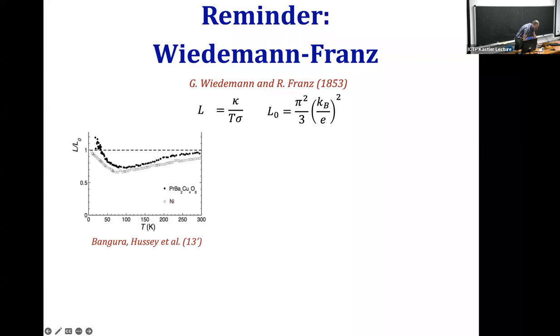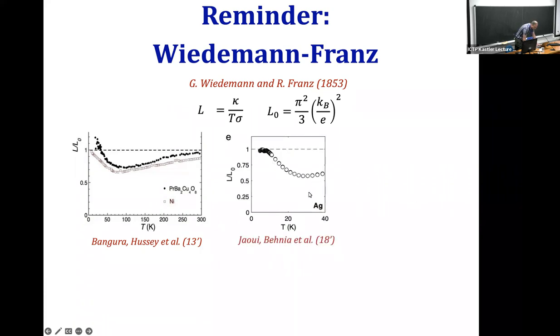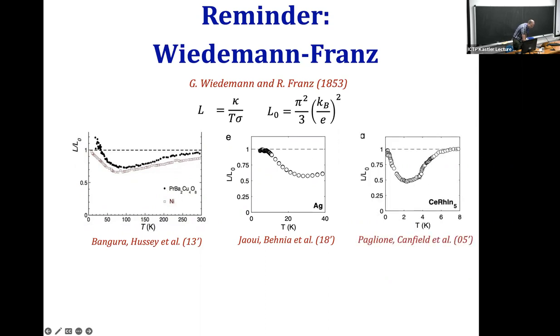Okay, and here are some examples. The open squares here are nickel. This is a quasi one dimensional metal. This is this Lorenz ratio divided by L naught as a function of temperature. You see this nice approach to 1. Okay, this is silver. Again, at the lowest temperatures, it approaches 1. And here's even a heavy fermion compound. You see this very typical behavior: it starts from 1 at the lowest temperatures, it deviates down, and it actually recovers back to 1 at higher temperatures. But here I'll mostly focus on the low temperature bit. And what's kind of striking is that in these different materials, this ratio really approaches 1 within a few percent.